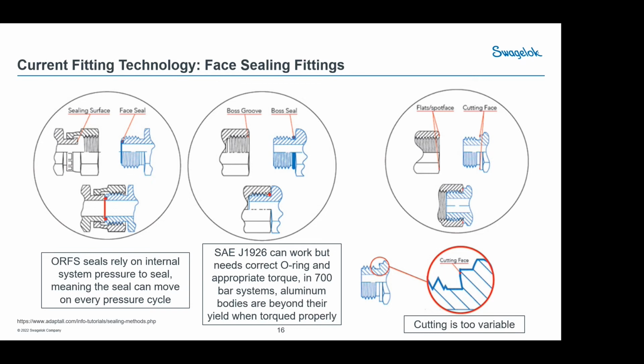One of the nice things is that you can bring this fitting up metal to metal, and you can make sure it's assured tight every time. However, you have a lot of permeation through these O-rings. The O-rings actually move under pressure cycles, so they have to remake themselves, so it can leak on one cycle and then seal itself on the next. So O-ring face seals in general are problematic. I've heard from many of the chief designers in the automotive world in Germany, don't even think about O-ring face seal inside of hydrogen systems. So that's a testimonial against them.